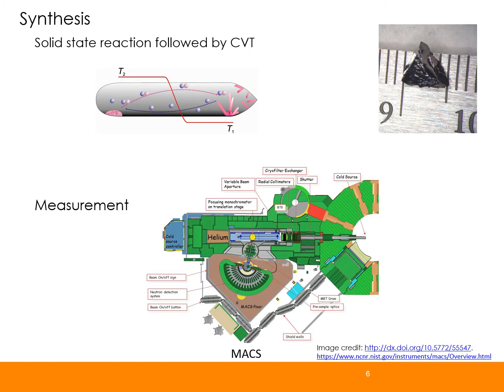Now we have the motivation of our project. For this we need the sample. The sample is grown using a conventional solid state reaction technique, followed by chemical vapor transport for the single crystals. I grew single crystals of around 100 milligrams in size, which is one of the biggest single crystals available of this material. And the inelastic neutron scattering measurements on single crystals were carried out at MACS, NCNR or NIST.